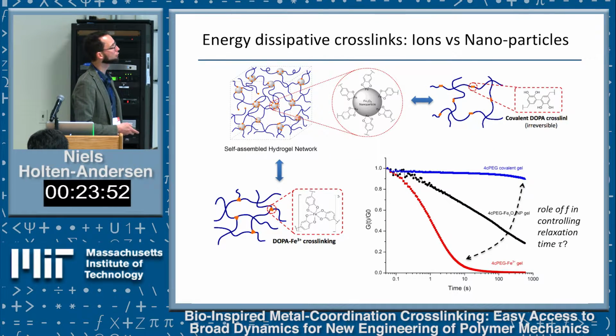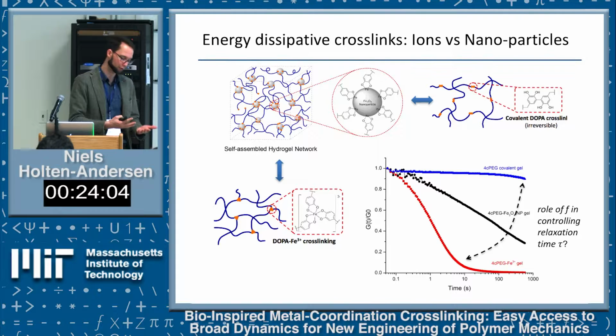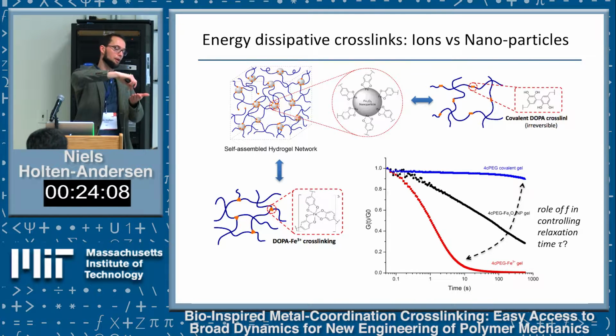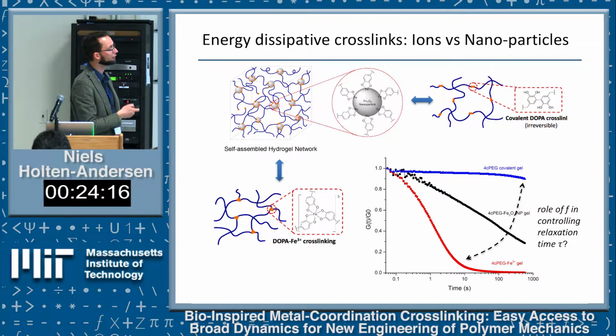This is a way of showing the 3 different materials we can easily play with to demonstrate this: a permanent covalent crosslink network, which I showed you earlier; the metal ion network; and the nanoparticle network. On the rheometer, instead of doing frequency sweeps, you apply a small strain and watch the stress in the material relax over time—it's called a stress relaxation test. You can really see the...